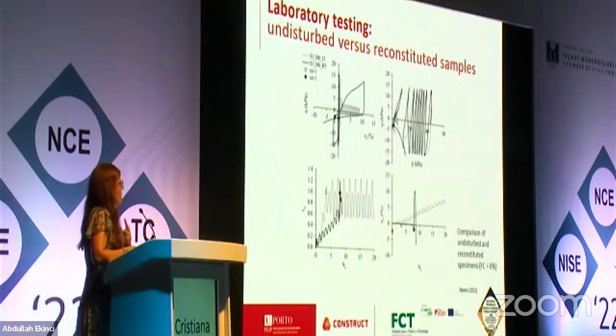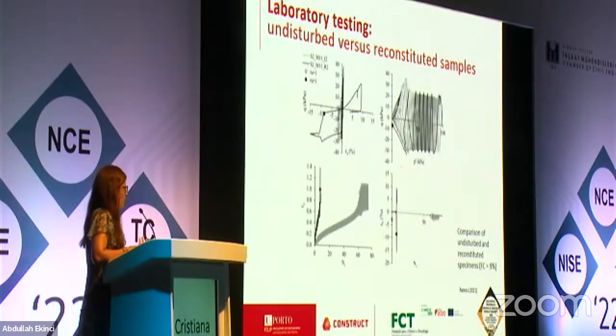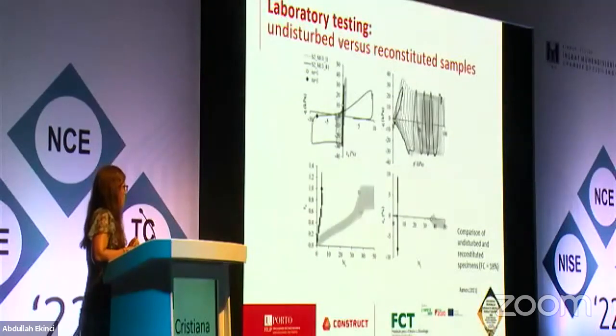And here we have some examples. What happens is that the undisturbed samples always have a different fines content, so a slightly different grain size distribution curve. I'm going to show you examples of 3 undisturbed and the respective reconstituted specimens. And the results are different because the fines content of each of these specimens is different. So we have, in this case, 6%, where the reconstituted specimen has a slightly higher liquefaction resistance, cyclic resistance. Then here we have the case for a fines content of 9%, where we see that the reconstituted specimen has clearly a lower cyclic resistance, and the same happens for a slightly higher fines content of